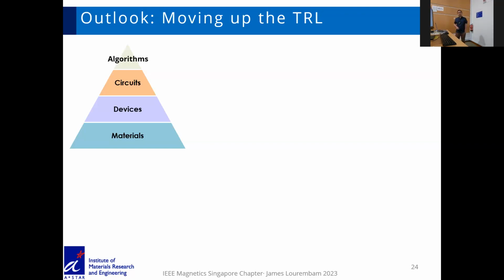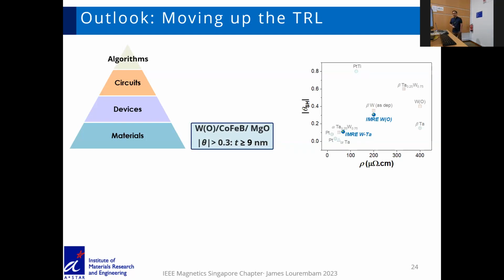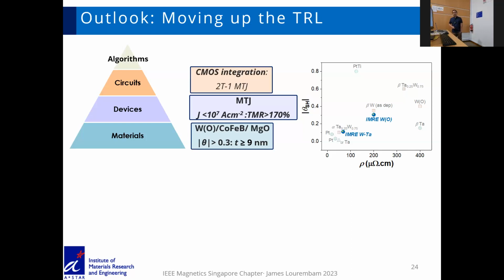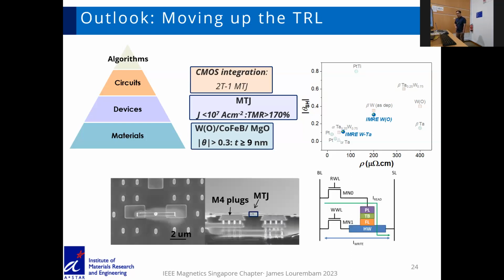The goal of this project is to build this technology starting from the platform of materials, then going on to devices, circuits and algorithms. We started with tungsten as a materials development and found that we could sustain this beta phase, high spin Hall angle system up to 9 nanometers. Then we developed MTJ with very large TMR and decent current densities. Finally, the goal is to get into circuit integration, which requires a 2-transistor, 1 MTJ device.